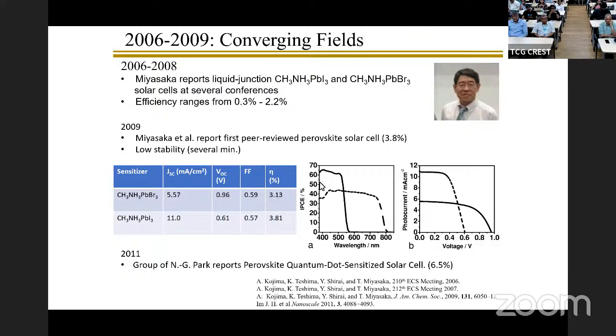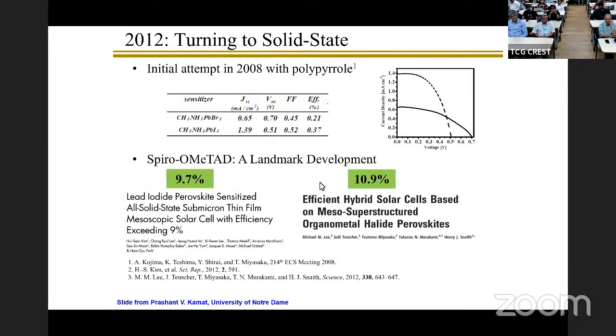Still, nobody took notice of it because it wasn't interesting, because solar photovoltaics based on silicon had already crossed 20% by that time. Till two papers appeared more or less at the same time, reporting about 10% or slightly higher efficiency. One from Henry Snaith's group and the other from Nam-Gyu Park with Michael Grätzel. And all hell broke loose. 10% was somehow the mental block that the photovoltaic community had, but once it crossed 10%, everybody jumped in.